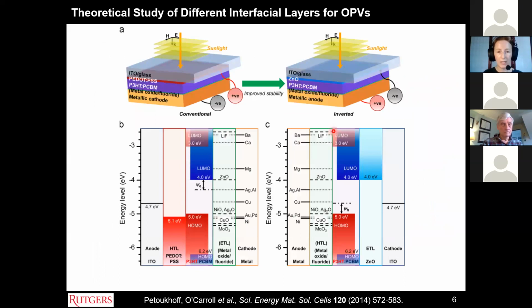And so originally in one of our early theoretical studies, we set out to calculate what would be the most suitable interfacial layers to use on a metal anode in an inverted optoelectronic device. In this case, it was a P3HT:PCBM based solar cell, so a very conventional organic polymer based solar cell. We looked at a range of potential metals as well as metal oxides and other interfacial layers that we could use to see which one would work best for optimizing the device performance. And these are just energy level schematics showing the range of the energy levels or work functions of the different materials that we studied.